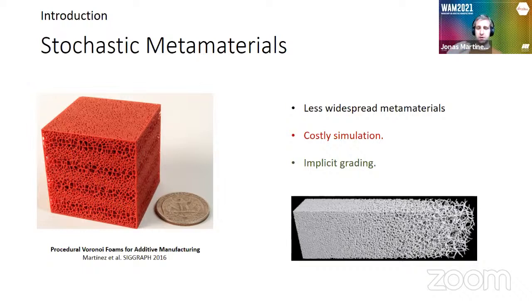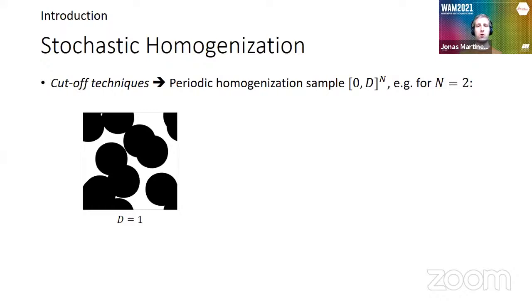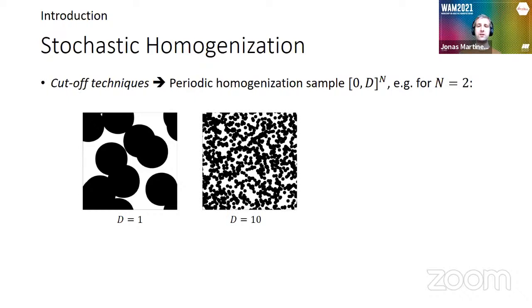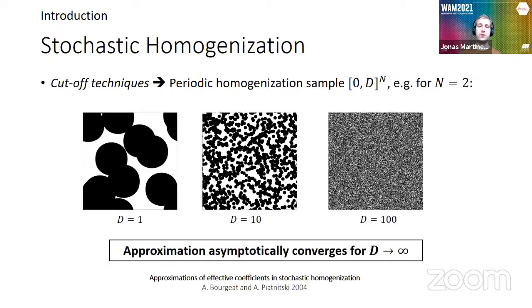So basically, in the remainder, you will see that with these stochastic metamaterials, we can do implicit grading, as opposed to periodic materials, where you have to take care of the boundary between the tile geometries. For stochastic homogenization, in order to compute the average behavior, we use a very simple technique called the cutoff technique, which basically consists of considering a periodic homogenization sample. And then the non-trivial question is what window will give you a good approximation of the average behavior of your random medium. And we know that for some kinds of random materials, this approximation actually converges.